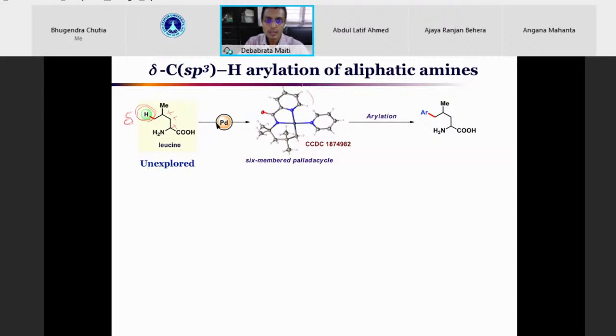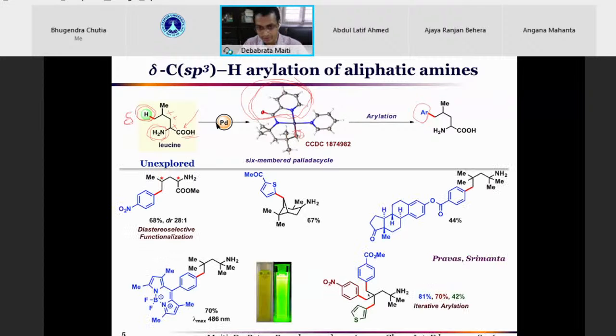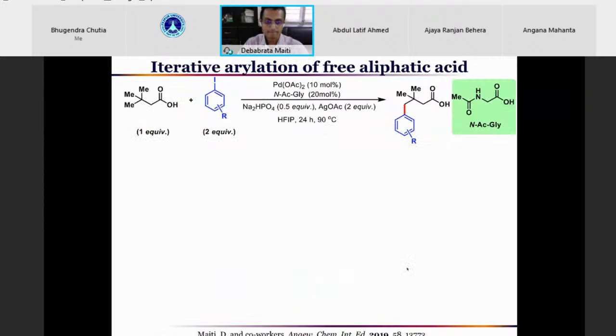Here we have introduced this pyridine carboxylic acid, as you can see, simple pyridine carboxylic acid on the amine unit. Previously, we were introducing the ligand from outside, that is 8-aminoquinoline with acid. Now we have introduced this pyridine carboxylic acid as this amine unit, and we see that the reaction can be done selectively at the delta position because metal is getting inserted selectively at the delta position. So delta CH activation happens and metal inserts, and then the reaction happens quite efficiently. Not only one arylation, you can keep on doing again and again and again. Iterative arylation can be done efficiently.